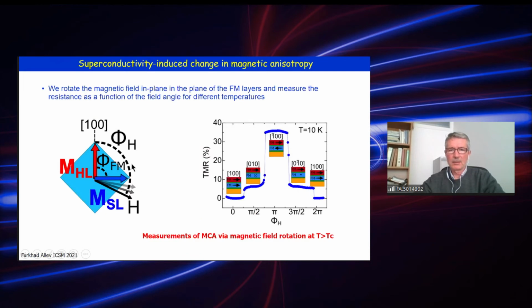Now let's turn to the second part, which is demonstration of the influence of superconductivity on magnetocrystalline anisotropy. The system is perfectly crystalline, so if we apply a magnetic field in plane, we see perfectly clean transitions. We have a second layer which is fixed, and the soft layer rotates. We see transitions between parallel, perpendicular in-plane, anti-parallel, again perpendicular, and vice versa. All this is in the normal state.